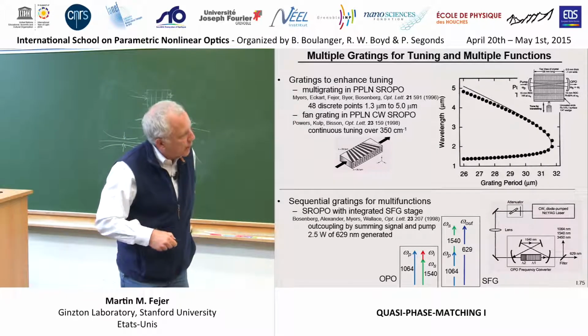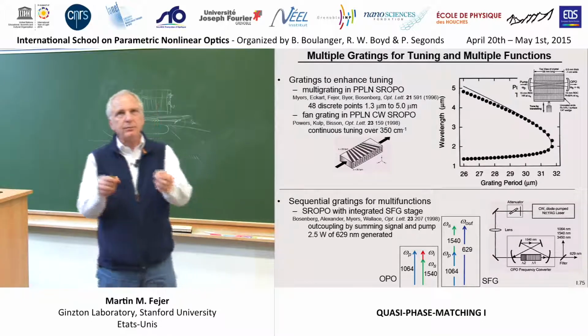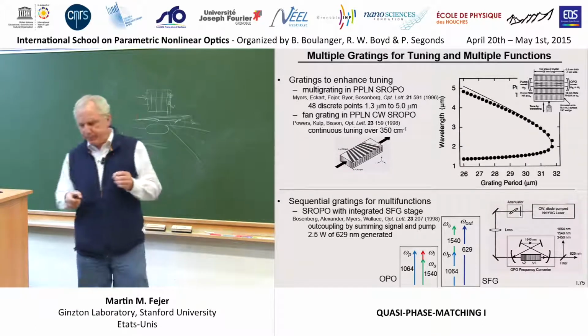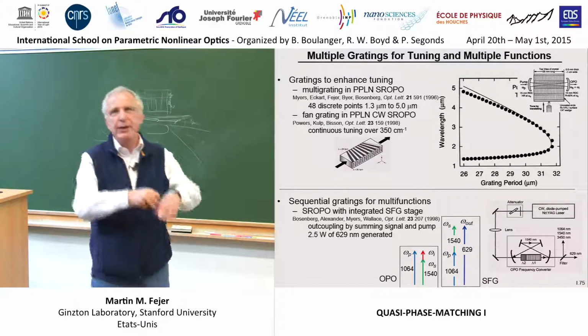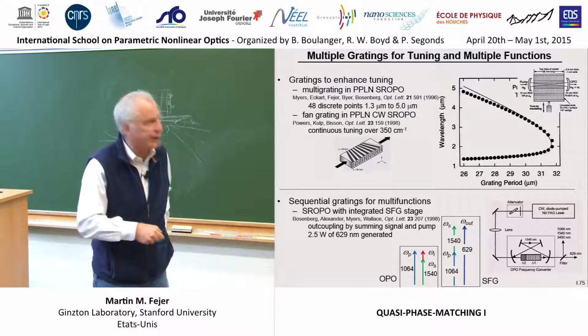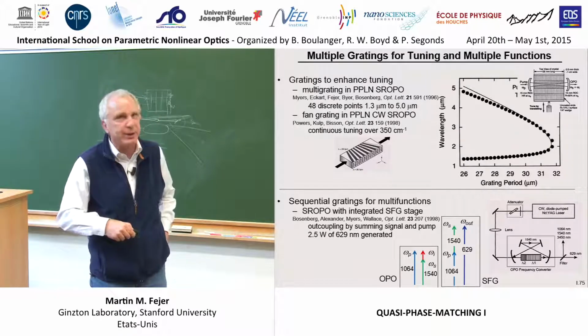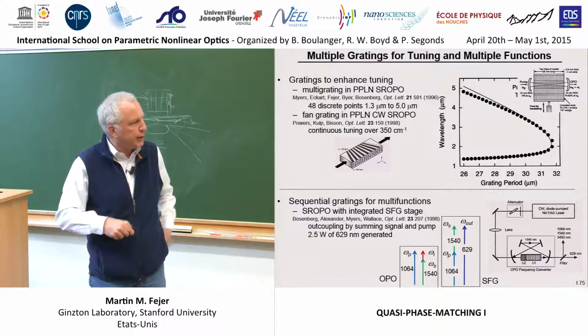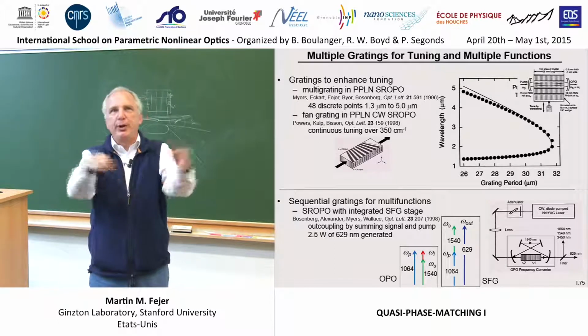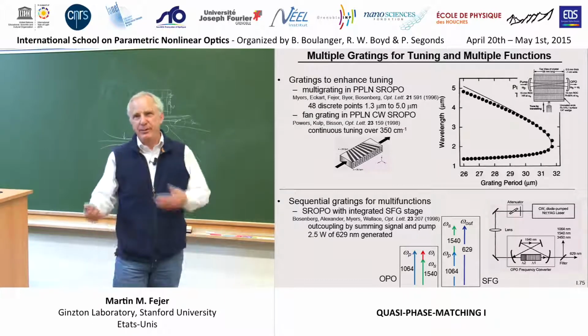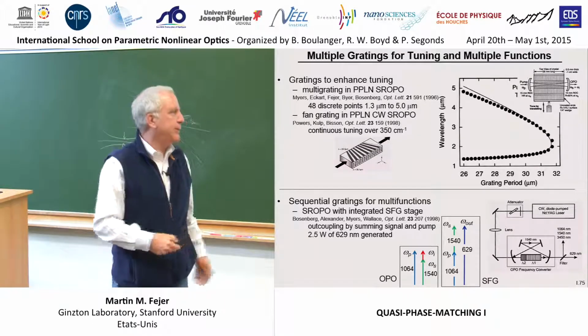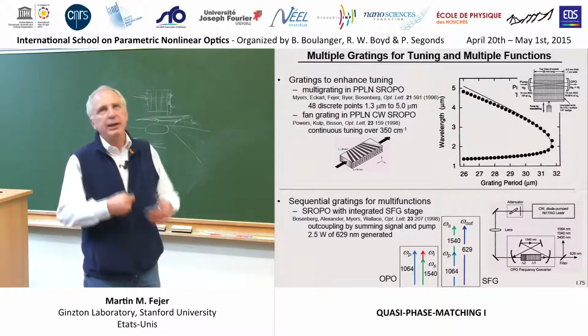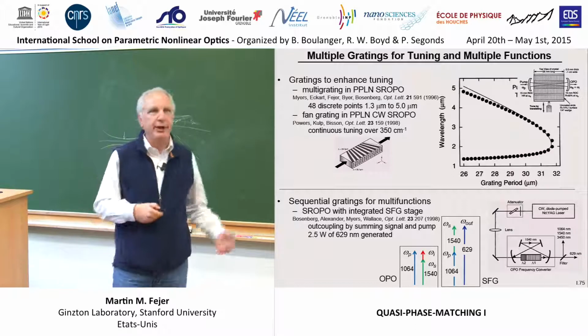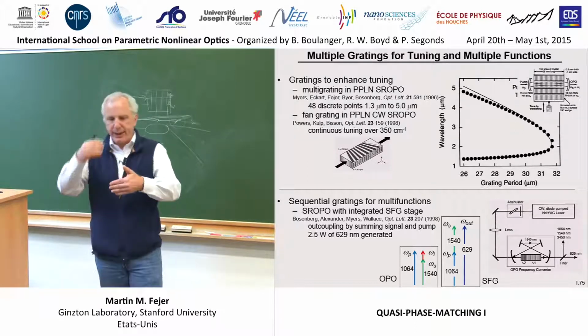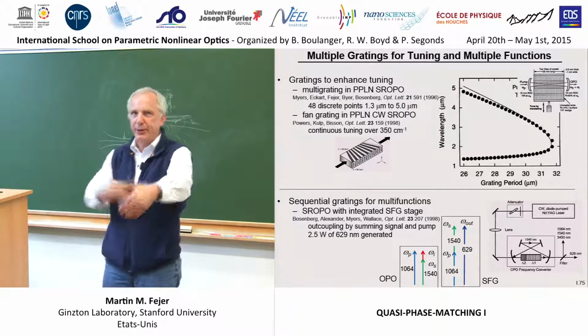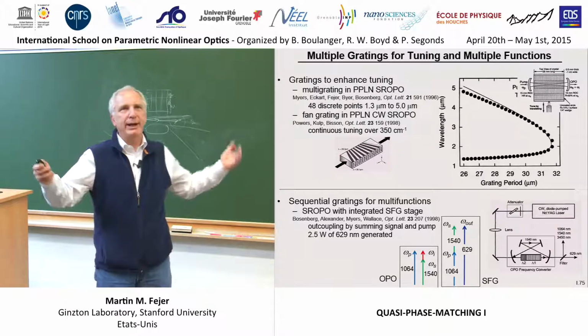The nice feature of putting both these things in one grating is that you don't have to worry about anti-reflection coatings, broadband, anything, extra losses from extra interfaces. It's still just 2 interfaces on your crystal, and the internal joint between these 2 QPM gratings is optically transparent and doesn't cause any problems with the interaction. And obviously there's a large variety of such sequential nonlinear processes you could engineer in. You can do third harmonic generation by first making second harmonic and then summing to the third, again, just by putting 2 gratings in a chip like that.